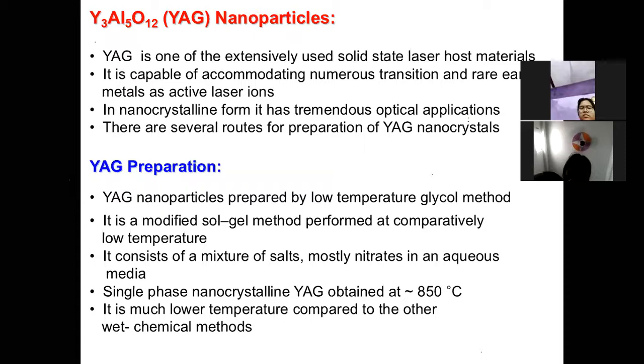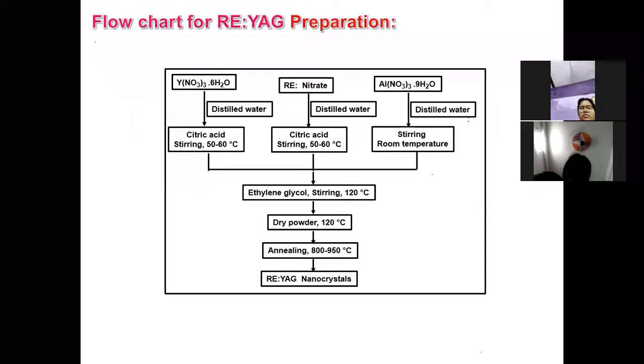So you can make these nanoparticles and use them in place of the crystal. Okay, so this is the flow chart of rare earth doped YAG preparation, because we dope all the rare earths, Nd and other rare earth materials, and the wavelength of that laser changes with the Re atom in it.